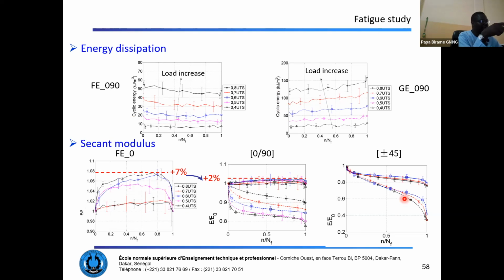That means that natural fiber, or let's say flax epoxy composites, when they are loaded, have an increase of their rigidity, which is linked to the fact that the microfibrils that are in the cell wall, namely the S2 cell wall, inclined at 10 degrees, or depending on the number of cycles, tend to align along the loading axis, so to go to 0 degrees. So when you look at the increase of the number of cycles, there is a realignment of the microfibrils, which gives an increase of the rigidity during the fatigue loading.